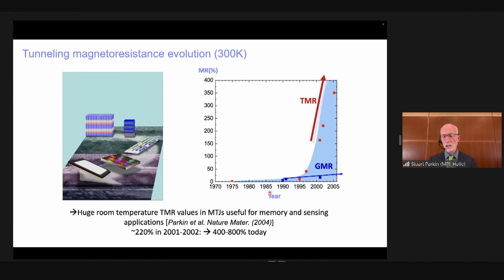In 2001, I showed this 220% at room temperature was possible. The change in resistance between the high resistance and low resistance state at room temperature. And today one can achieve even higher changes in the resistance of this material. This is useful for building advanced sensing devices. Now, when you build a tunneling device, what is critical is the thickness of the tunnel barrier. That will determine the resistance of the device. And at useful dimensions today, that means the tunnel barrier has to be less than 1 nanometer thick. And the so-called resistance area product has to be extremely tiny. And we have been able to achieve resistance area products lower than was ever possible before in any type of tunneling junction device. So this was a very important achievement.